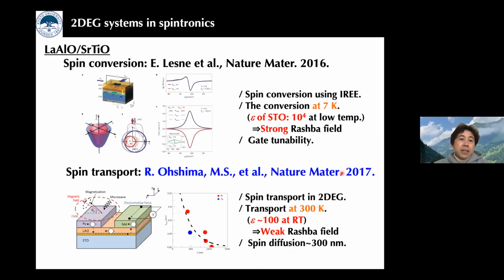The third example is a 2D system. 2D means a two-dimensional electron gas. And the famous system is the lanthanum aluminate, strontium titanate bilayer, and a two-dimensional electron gas can be formed at the interface of these two insulating oxides. Both are insulating, but the 2D gas is formed at the interface because the dielectric constant of strontium titanate is quite large at low temperature. And this allows the strong Rashba field formation, and this allows the creation of the 2D system.